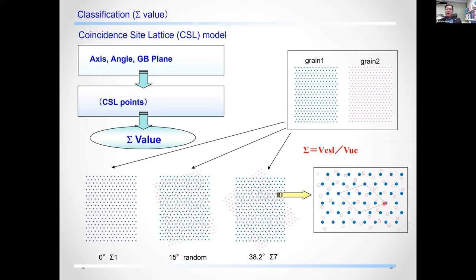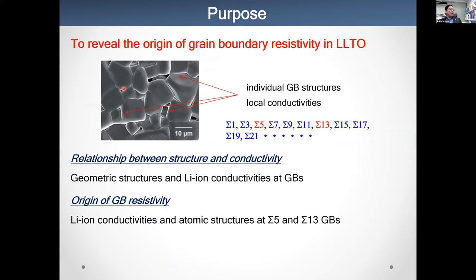match to form a supercell. This is the so-called coincidence site lattice. The sigma value is defined by the volume of the CSL divided by the volume of the unit cell. Therefore, when the sigma number is small, this means that the boundary is very coherent. In actual materials, there are many boundaries which have different sigma values. Today, time is limited, so we just pick two types of grain boundary: the sigma 5 coherent boundary and the sigma 13 boundary, whose sigma number is larger than sigma 5, which corresponds to a more general boundary, to reveal the origin of grain boundary resistivity.